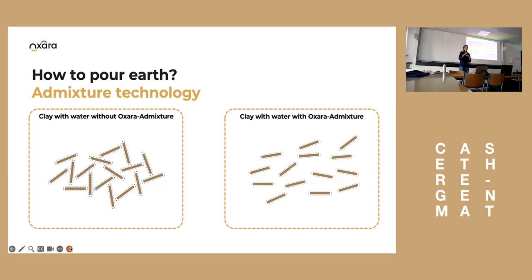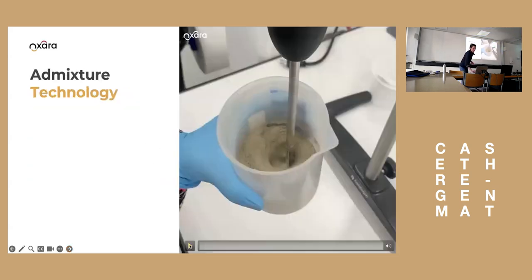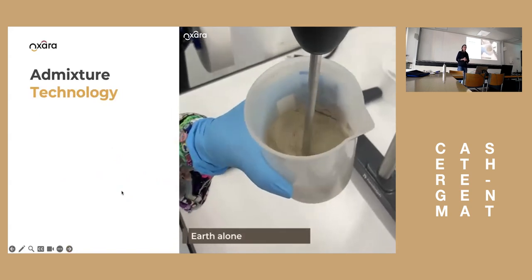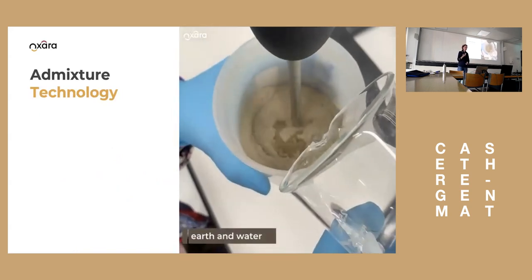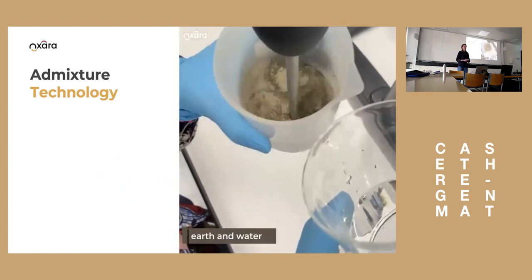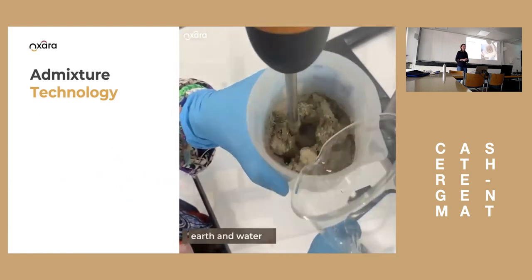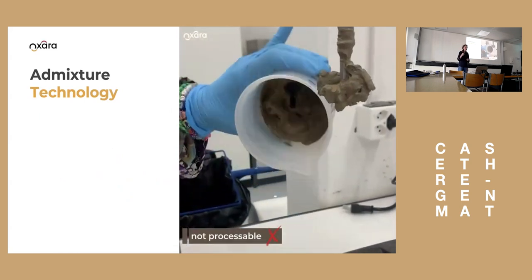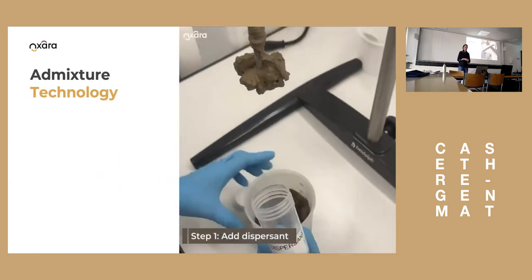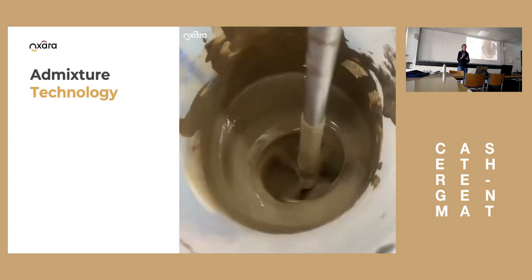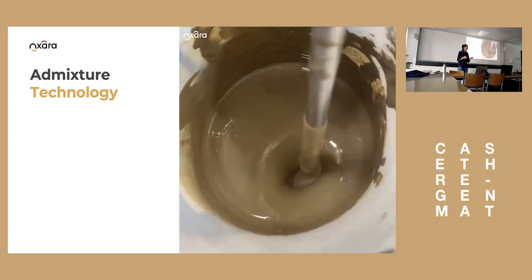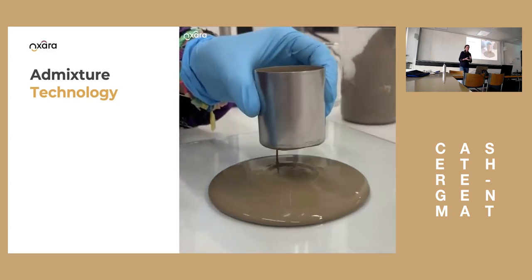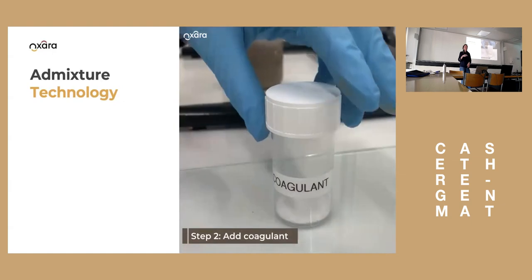And then if you want to stop the fluidity because you have placed your material, you want to reverse that effect, and you do that by adding a coagulant that then consumes the dispersant. And here we have a lab demonstration of how this works. First you mix the dry earth with a certain amount of water, and then you mix. With this amount of water it's not fluid, because it was not enough water. Then you add the dispersant and mix it in. Then you can see that you get a very well flowable paste that is also suitable for processing on a construction site. And then you add a coagulant.